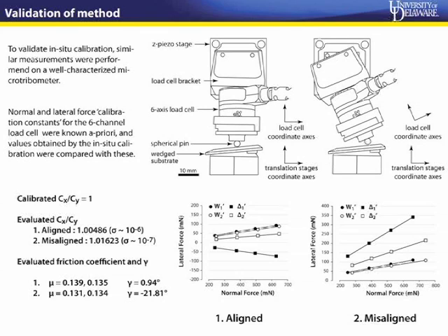The ratio is 1. So what we do is scan. In this case, the contact was between a lubricated glass slide and a 1/16-inch steel ball, wedged up to an angle, and we determine the angle again using the indents. We try to replicate the measurements that we were planning on doing on the AFM with this well-characterized microtribometer, and we end up with similar load-dependent curves for W and delta. When we go through the analysis, the iteration and the solver, the CxCy values that we end up with through our method are remarkably close to the stipulated value of 1.